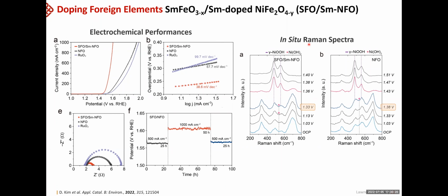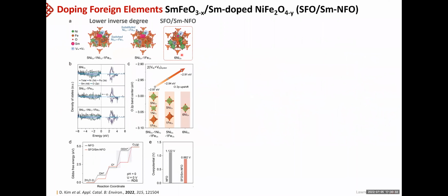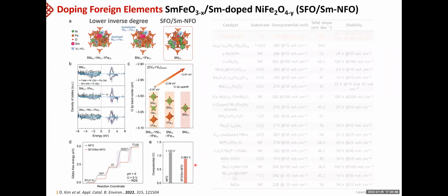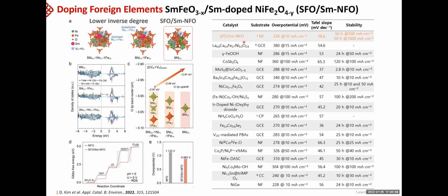And from the in situ Raman, we also observed the similar effect that with our main sample, the transition to the active species occurs at a lower potential. And from the DFT calculation, we could rationalize that this is because when you have a more inverse structure induced by the samarium doping and interface construction, actually the oxygen 2p band has been upshifted, and that even changed their reaction mechanism. And then the overpotential is expected to be lowered. And that shows really impressive performance, even at the high current density and very good stability.